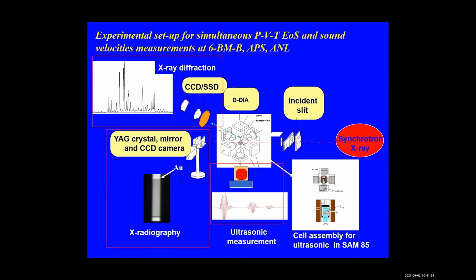This is a schematic diagram of the setup for the equation of state and elasticity measurements at the 6-BM-B beamline at the APS. The pressure is generated by the DIA-type cubic anvil apparatus interfaced with the X-ray that enters and exits the sample chamber through the anvil gaps. Attached to the bottom part of the press, one of the anvils is a dual mode lithium niobate transducer for generating P and S waves into the sample and receiving the reflected signal.